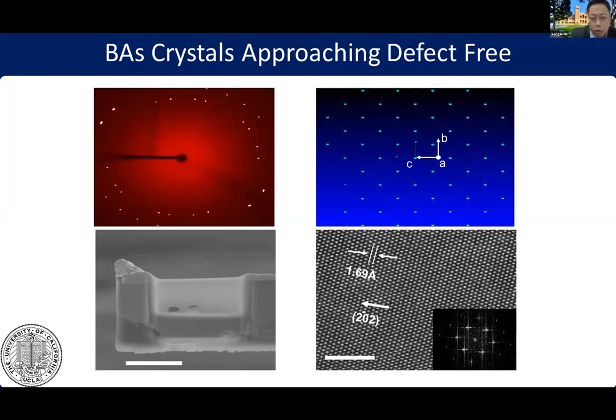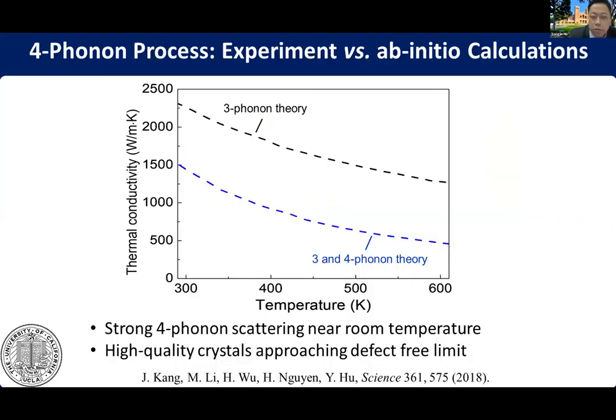So then the question is why for such a high quality crystal, thermal conductivity is still lower than the initial theoretical predictions. So to make a long story short, by comparing experiment with different ab initio calculation results, we found that the 4-phonon process is very strong in these materials.